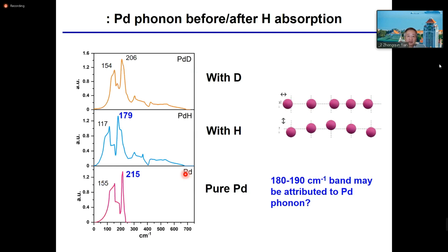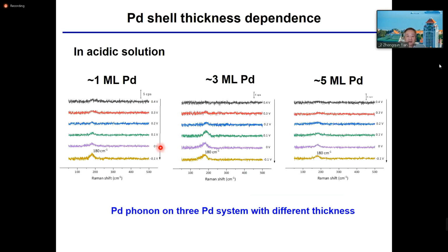Then we asked Professor Pan Feng to carry out a very, very preliminary calculation, because we asked him 2 days ago. He briefly provided a result and gave us some trend that with hydrogen or deuterium, this peak possibly can shift a little bit. As you can see, we also checked the thickness dependence, and the situation is quite similar, with no considerable difference.